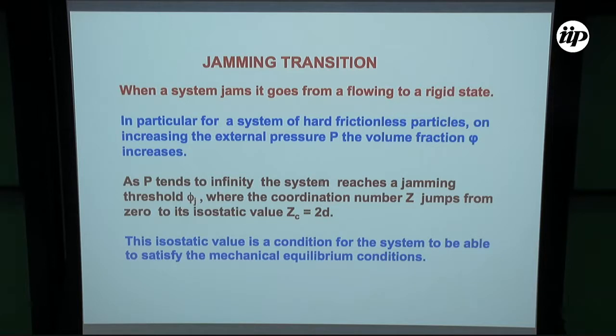In particular, just to fix the ideas, for a system of hard frictionless particles, if you increase the external pressure P, the volume fraction increases. And as the pressure tends to infinity, the system reaches a jamming threshold phi j, where the coordination number zeta jumps from 0 to its isostatic value zeta_iso, which equals 2d, d being the dimensionality. This isostatic value is a condition for the system to be able to satisfy the mechanical equilibrium conditions.